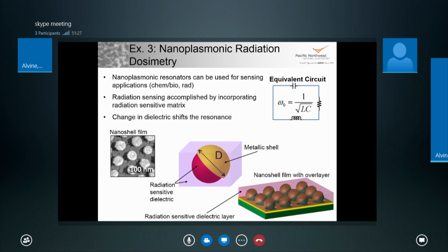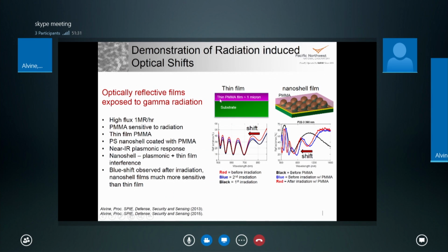So we were able to look at films created with acrylic, very thin acrylic films. You don't see much of a shift in just a thin acrylic film—there is a slight shift, but you can't see it because it's so slight. But when you incorporate the nanoshells into the film and do the same exact experiment, you get a very dramatic shift in the interference fringes from the film, because of the resonant enhancement of the nanoshells.